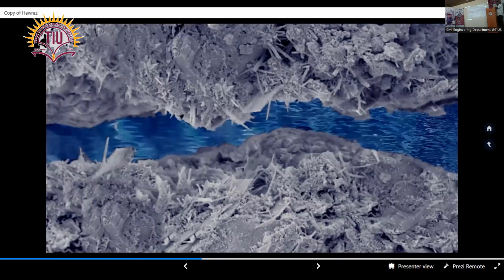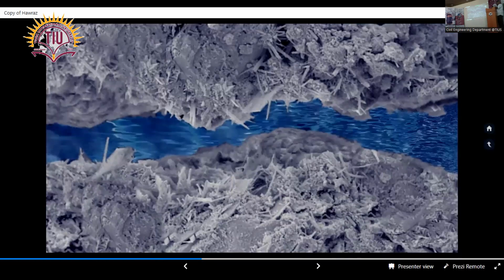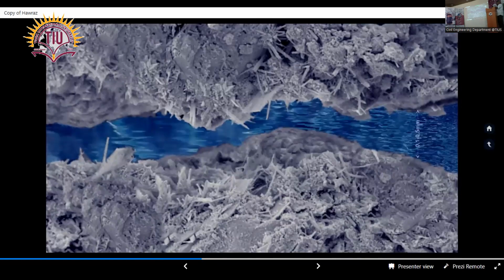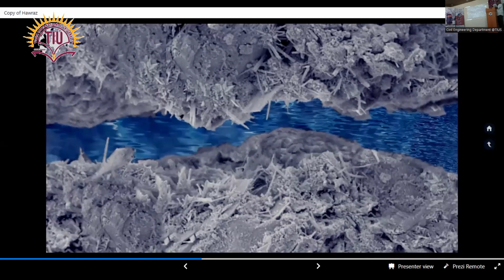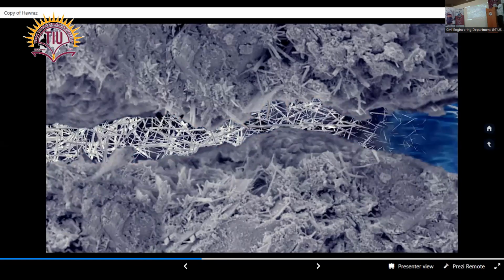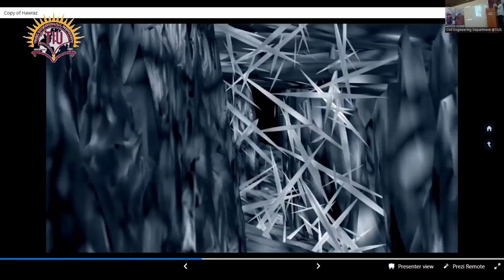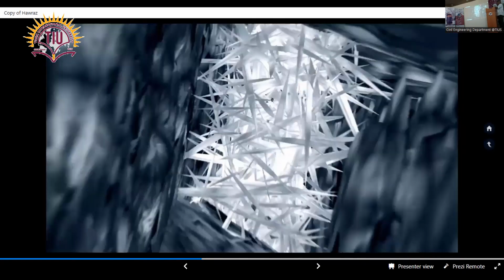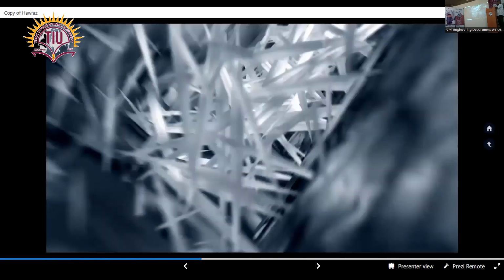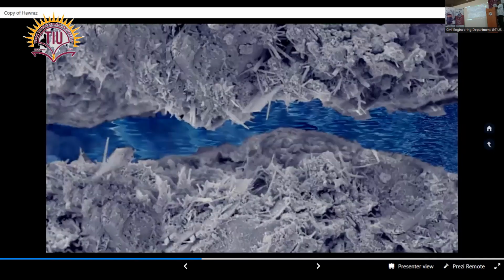These pores have a width between 0.1 millimeters and 0.05 millimeters. When Penetron products are applied to the concrete, the chemical reaction that follows causes these voids and cracks to be filled with insoluble crystals. Water is unable to pass through these crystal formations, and as a result, the concrete becomes waterproof. The ability of Penetron products to penetrate deep into the concrete structure, even when applied from the negative side and against high hydrostatic pressure, is the result of a complex chemical reaction involving osmosis, dry particle reactions, and Brownian movement.